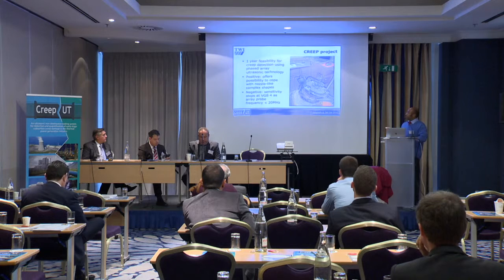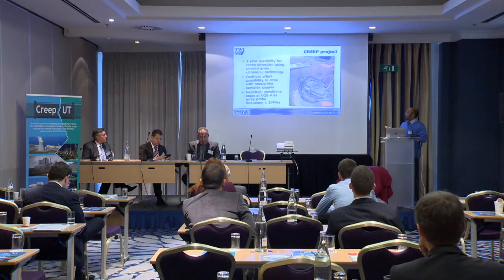So the CREEP project, which was funded for a very rapid turnaround, a 1-year feasibility, led to the development of this scanning system and the use of a 2-dimensional phased array probe. So this is a 256 element phased array probe that was able to steer the beam in the 2 planes in order to deal with the complex shape weld geometry that I talked about earlier. So that project essentially led to some positives, which was that it was possible to deal with nozzles, and from that on, that stream of work is a separate approach that led to some other developments.